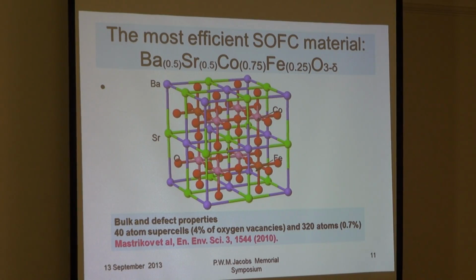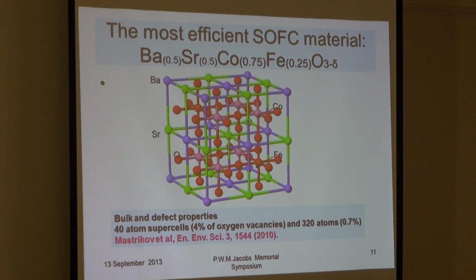So it's nothing special. This is just a sketch of the 40-atom supercell. We just remove some oxygen atoms from here and obtain essentially a defective structure that we calculate. And I would like to stress that this material, barium strontium cobalt iron, BSCF, at the moment is the most efficient material.